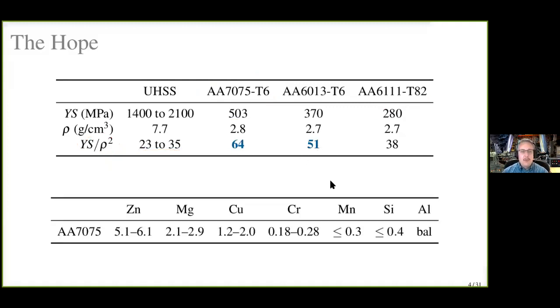Well, let's first talk about what the composition of 7075 is. The primary alloying additions are zinc and magnesium, and these together form very effective precipitates. Usually we call them an eta or eta prime precipitate. I'll talk about those a little bit later, but you notice 7075 also has some copper addition. So to get the strength, we have to have the proper temper condition, the T6 being the highest strength temper condition for 7075. So we not only have to make the part, we have to get the part into the proper temper condition to get the strength we want to make that material an advantage.